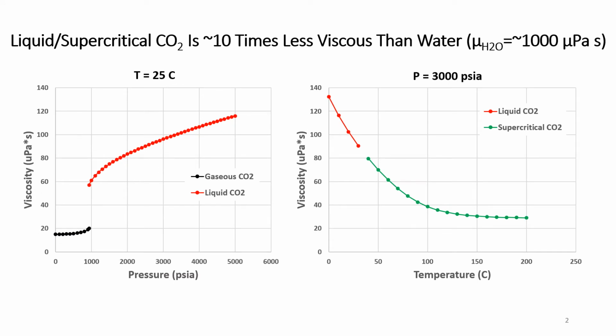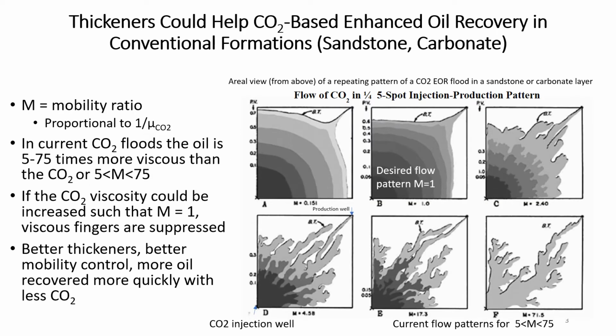One of the unique properties of both liquid and supercritical CO2 is how low its viscosity is. It's about 10 times less viscous than water. However, in some applications that people want to use supercritical CO2, such as enhanced oil recovery, the viscosity is actually too low to be useful. The ideal recovery fluid has about the same viscosity as the oil it is replacing, but CO2 is about 10 times less viscous than that.